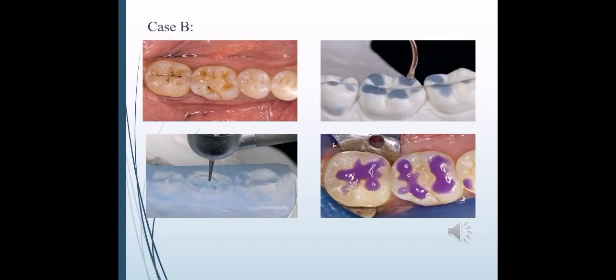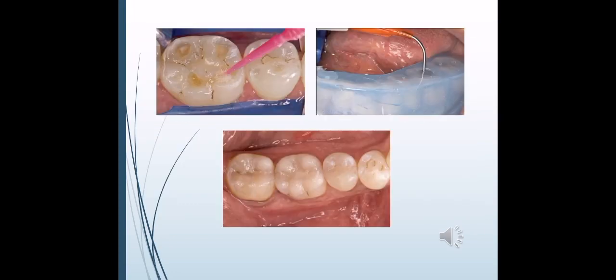Sometimes patients might complain about having invaginations on the occlusal surfaces of their molars due to bruxism. So after the correct shade is taken, a diagnostic wax-up is made to establish the original anatomic form, and a clear polyvinyl siloxane matrix is fabricated and a small opening is made above each tooth to be restored. Then the teeth, including enamel and dentine, are etched with phosphoric acid for 15 seconds. Then an adhesive was applied and allowed to dwell for 10 seconds, dried for 5 seconds, and light cured for another 10 seconds. Then the A1 shaded Filtek Supreme was injected through the small opening above each tooth and was cured for 40 seconds, as we can see here in the post-operative view.